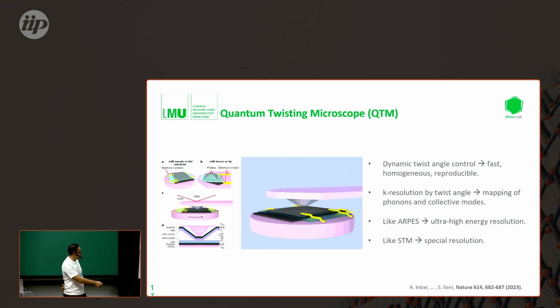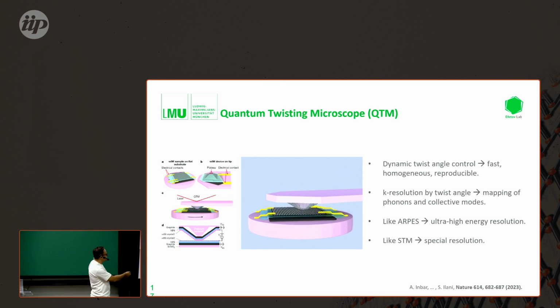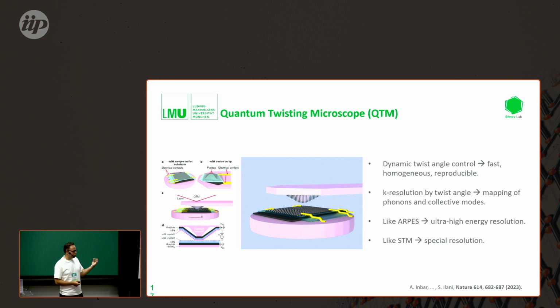So when we saw this technique by Shahal, we were quite excited. And as I will show you in a second, what this technique really shows is that you can get the k-space resolution of the spectral functions, because by rotating the devices with respect to one another, you can introduce a k-space vector between the Fermi surfaces, and this way change the k-space separation between them. It allows us to do spectroscopy similar to ARPES. However, unlike ARPES, with a bit better resolution, because it's a purely electronic measurement, not a photo-excited measurement.